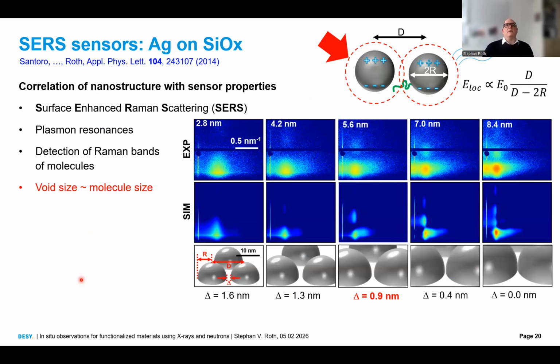So, staying with silver on silicon, this is the first functional material we use. Silver, like other metals, has a plasmonic resonance. When you put two silver clusters very close to each other, put a small molecule between these clusters and shine a laser on, you can excite the Raman vibrations of this molecule, and these Raman vibrations are enhanced by the electromagnetic field created by the plasmon resonances of these small nanoclusters. This method is called surface-enhanced Raman scattering. So you make a thin metal layer, put a droplet with your molecule on, and you can detect trace molecules.